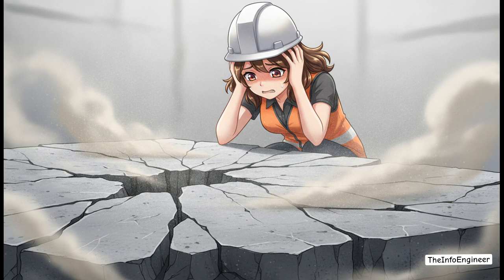Here is the bottom line. If water evaporates from your slab too quickly, that vital chemical hydration reaction just stops, dead in its tracks. It's a premature halt. And what are you left with? You're left with weak, brittle concrete that's absolutely plagued by surface dusting, scaling, and severe shrinkage cracking. It's a nightmare. That is exactly why managing moisture, whether that's through wet curing or sealing compounds during those critical first few days, is simply non-negotiable.